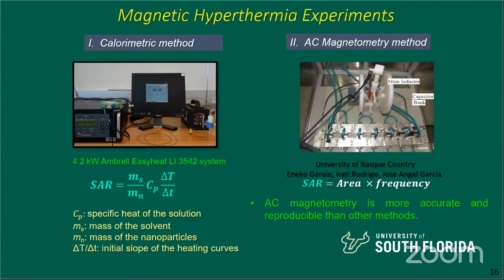So basically, we do it in two different ways. In our lab, we measure the heating of these nanoparticles by using the calorimetric method. Here's the AC magnetic power supply. And that's the coil right there. We put the particles in there. We supply a large amplitude AC, and then we measure. What we do is stick in a temperature sensor here, a thermometer, and then measure the change in temperature as a function of time, and we can get the SAR from this relation, okay?